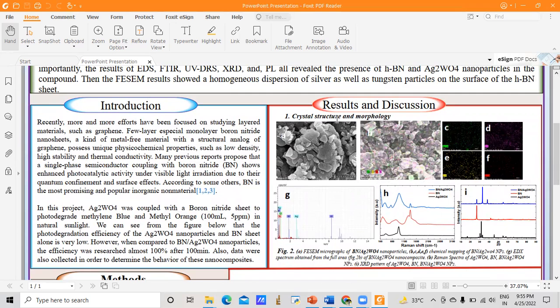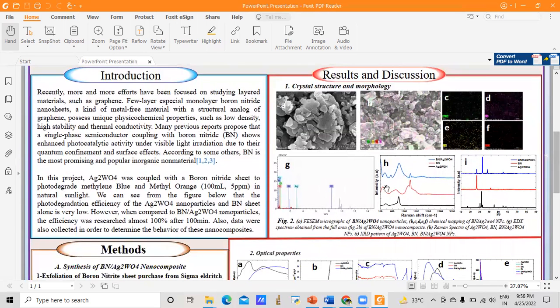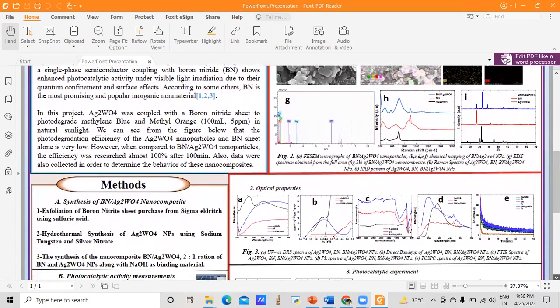So here are a few characterizations we have made: the crystal structure and morphology. The first image is the FESEM. Then the second one is the chemical mapping of BN-Ag2WO4, and here we can see that the silver, oxygen, tungsten, and nitrogen were detected by our EDX machine. The boron is not detected because our machine is not able to detect boron. So here is the corresponding EDS analysis, followed by the Raman and then the XRD of the different nanocomposites.